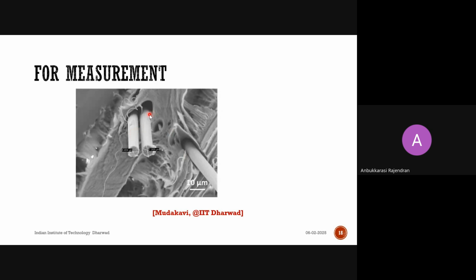So as it is, you can take it, but if it is a charging material, like a non-conducting material, it is supposed to be coated with a conductive material like gold. So before taking it into my SEM machine, you must do the gold coating over it. That is a conductive coating to avoid the charging of the sample. So yes, we can do the analysis of polymer.